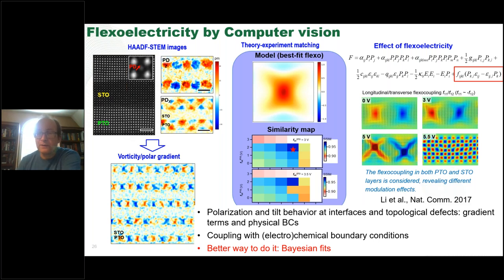And flexoelectricity is one of the things that is very important on the nanoscale, but very difficult to measure macroscopically because it tends to hide behind the electrochemical phenomena. So it turns out that if we use machine learning method to extract the average shape of the vortex and then match it to theory, we can get a very good estimate for the flexoelectric constant tensor. So it feels great.